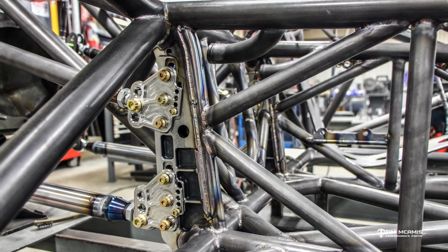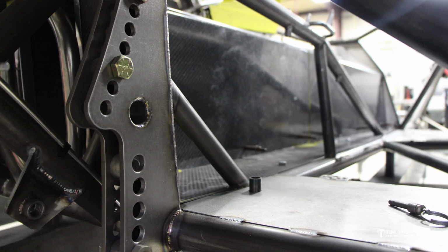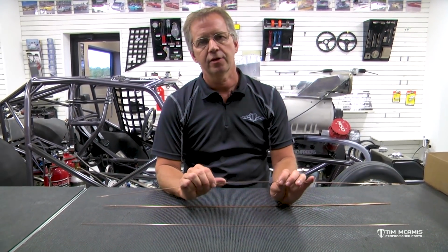But then we also have an ER80S2 rod, which we only use in one part of the chassis, which is the four-link brackets, and really just the adjustable four-link brackets, because the standard plate brackets with the holes in them are the same material. They're going to be a normalized 4130. So we'll use a 70S rod there. For instance, if we're welding on the four link brackets, you might want to use a 3/32 because you're going to be welding a 1/4 inch bracket on, you're going to need some more heat. And you're welding it to an 083 tube, so you can put a little heat to it and use a 3/32 rod to make a nice bead. But those adjustable brackets, that base part of the bracket that welds to the chassis, it's a harder material. So we want to use an ER80S rod for that. So we keep the 80 in just a 1/16 diameter, and that's what we'll use exclusively to weld those brackets on.